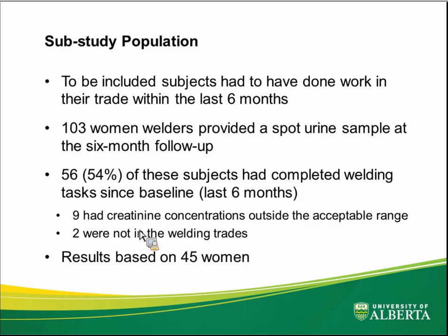But not all of these women were actively working in their trade. And because we were interested in welding exposures and urinary metal concentrations, we limited it to people who we knew had been working in their trade in the previous 6 months. Of these 56, 9 had concentrations that were outside the acceptable range for creatinine. So they were either too concentrated or too dilute. And so these are limits that are set by WHO and accepted by the ACGIH. So we did exclude 9 more subjects, and we excluded 2 additional who actually weren't in welding trades and somehow had snuck under the wire.